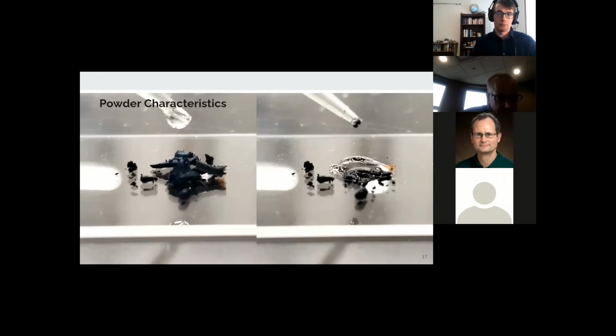The yield of the powder was on par with other non-thermal plasma synthesis systems, which was on the milligram order of magnitude. A typical 1-hour run would allow for the collection of between 6 and 10 milligrams of powder, but would depend on how much hydrogen was used because the hydrogen consumes part of the precursor. The powder collects on the mesh wires, so its collection varies linearly with cross-sectional area covered by the mesh. Because the nanocrystals collect on the mesh first and deposit upstream from there, the gas flows between the nanoparticles, and the powder remains in a porous open fractal geometry.